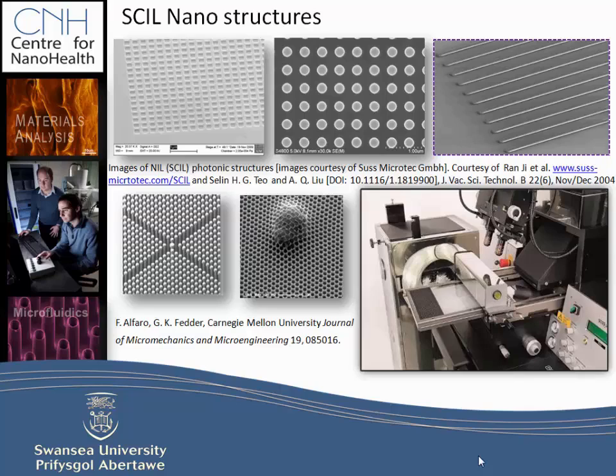It's a new type of imprint lithography process developed jointly by SUSS MicroTec and Philips, and enables you to produce these arrays of nanostructures down to about 30 nanometers, but crucially over large areas. So we can produce structures on up to 8-inch wafers. Okay. And what you can see here is an interesting example where you have a particle under your imprint, but the imprint pattern is transferred over the particle. So the nice thing about this process is you don't get voiding as you do in some imprint techniques.